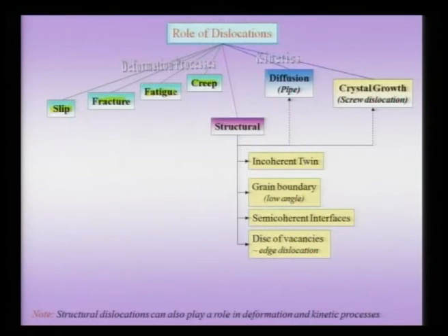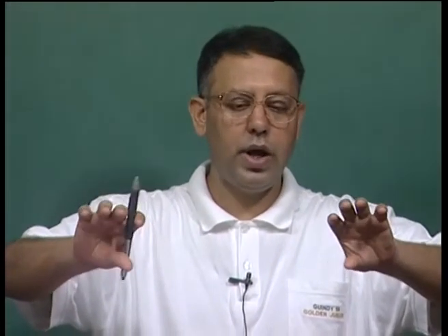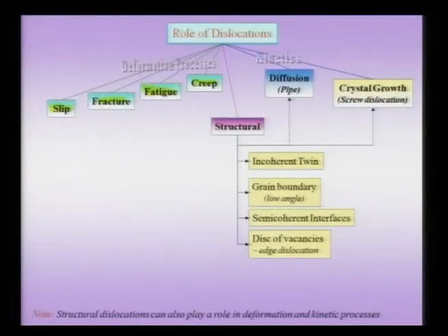They also play a very important role, for instance, in nucleation of fatigue cracks, and you know, fatigue loading is when you have an oscillating sort of stress field. That means it changes sign, or it could go through an up and down, and in that case these dislocations could move and come to the surface, cause surface steps, which could act like surface intrusions and extrusions, which would actually act like cracks. So in other words, the very process of dislocation motion, which is of course happening by slip at the microscopic level, can give rise to a macroscopic crack, or a slightly larger scale microscopic crack, which is related to fatigue cracks. They also play a very important role in creep and related phenomena.